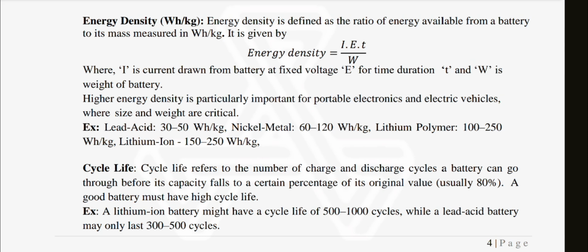Higher energy density is particularly important for portable electronics and electric vehicles, where size and weight are crucial. Example: lead acid 30 to 50 Wh per kg, nickel metal hydride 60 to 120 Wh per kg, lithium polymer 100 to 250 Wh per kg, lithium ion 150 to 250 Wh per kg.